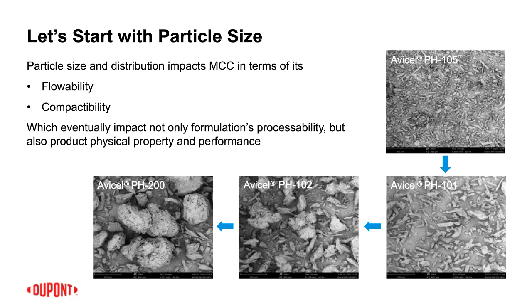Typically, customers use Avicel PH 101 more in the wet granulation type. It doesn't require much particle flow, good flow property. And Avicel PH 102 is a common grade used a lot in direct compression because it gives decent, good flow property. And if your formulation really has a flow issue, then we can help customers with Avicel PH 200 because it can really boost up the flowability of the formulation. So okay, you can see a general guideline will be between Avicel 101 used in wet granulation type of process, and Avicel PH 102 using direct compression. Thanks.